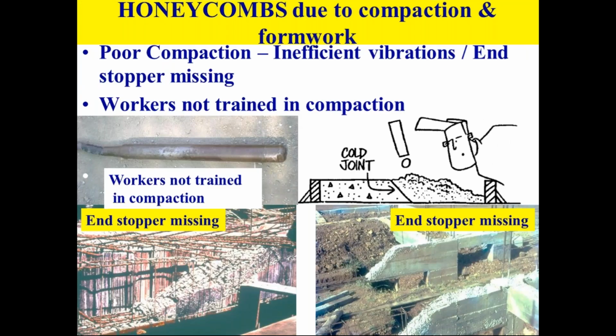Next. Next. Yeah, you can see that. Honeycombs due to compaction and formwork. Poor compaction can occur if the mix does not have proper workability or if proper needle vibrators are not being used. Many a time, people avoid putting end stoppers, and the worker has no choice but to refrain from vibrating the mix at the end of the beam because there is no end stop. You can see that in the photographs below.